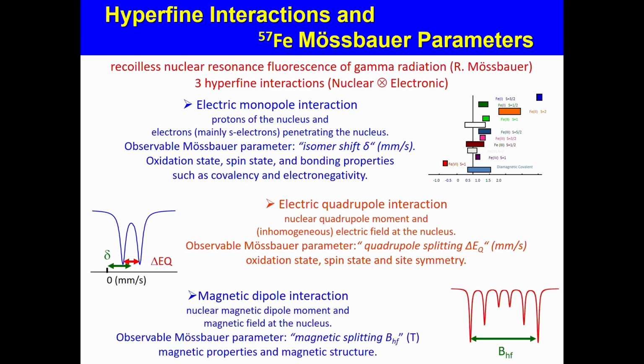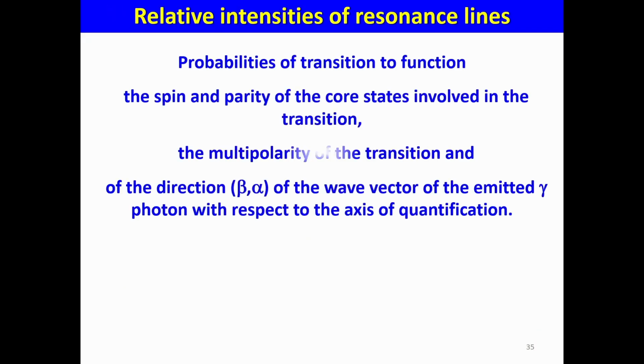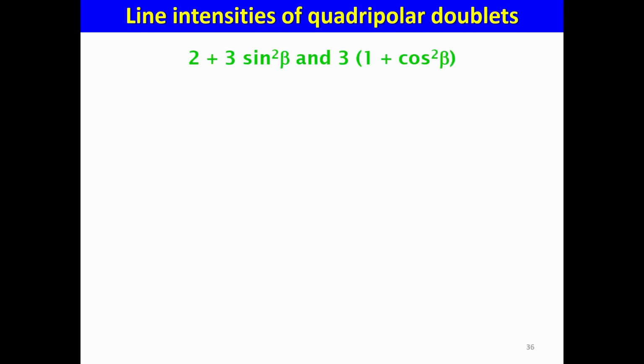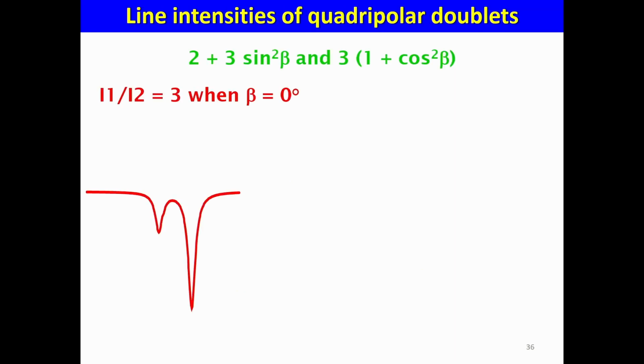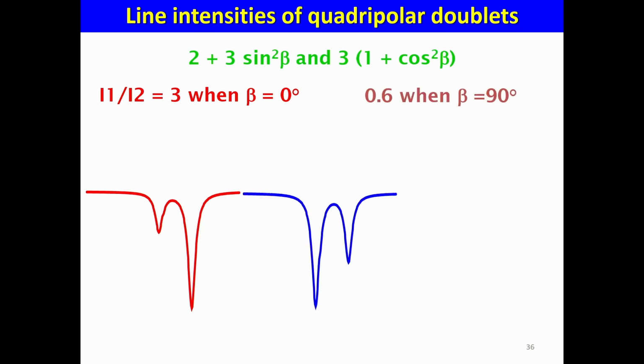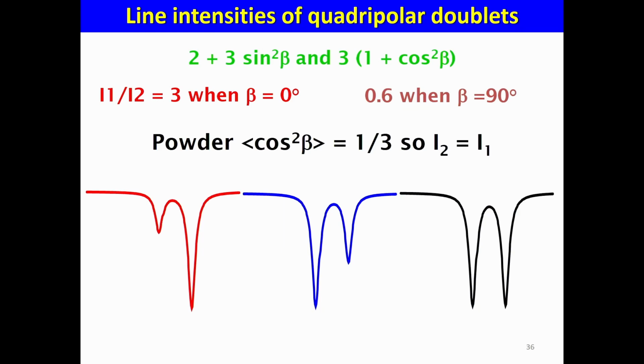Okay, and then the last point. One point that is also interesting is to analyze the intensities of lines, because we will see after that it's very important to know them. The same, you have to apply quantum mechanics using the Clebsch-Gordan coefficients, and you will arrive at such things in the case of quadrupolar doublets. So you have 3 cases.